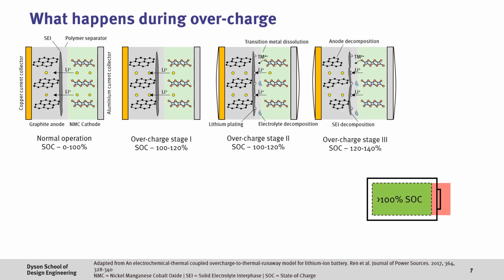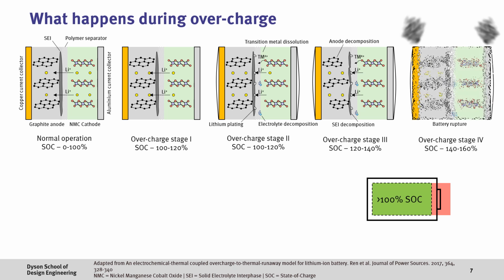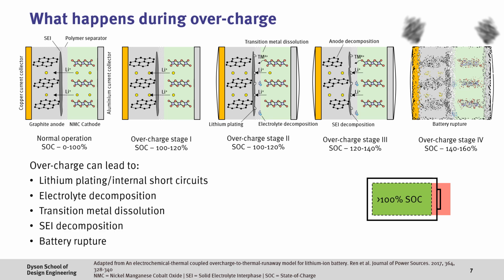Then, as we continue to overcharge the battery, this can lead to the decomposition of the protective solid electrolyte interface layer, as well as the decomposition of the anode. These processes combined can lead to significant exothermic processes, which ultimately lead to the battery rupture. Therefore, overcharge can lead to lithium plating or internal shorts, electrolyte decomposition, transition metal dissolution at the cathode, SEI layer decomposition, and ultimately battery thermal runaway.